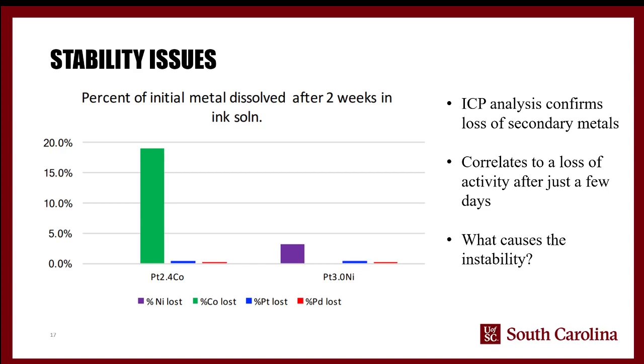It may be the case that it's a very high energy particle that forms, and because of that, the energetic strain needs to be relaxed in some way, and the way that it ultimately does this is by releasing some of the secondary metal that's involved. It may be that the reason for the high activity is that these secondary metals have some dangling bonds, which also cause them to be unstable. But that's something that we're working on.